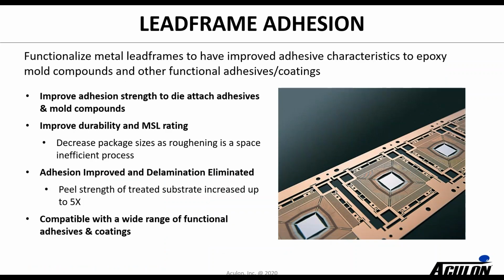So digging a little deeper on the lead frame adhesion, like I said, it's good for both mold compounds and die attach. And this is really the main motivation: to improve moisture sensitivity level rating, which rates how well the package stays together in different temperature and humidity environments. And so we've been able, in a lot of cases, to increase the MSL rating of the lead frames and really improve adhesion of both the die attach and the mold compound.